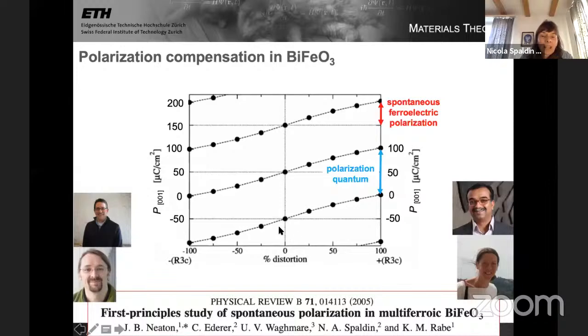And actually, this is something we knew already, although I guess I had personally not really registered the implications of this in 2005 with Jeff Neaton, Claude Ederer, Umesh Waghmare, and Karin Rabe, when we calculated the polarization as a function of the distortion in bismuth ferrite. Here you see the different branches of the polarization lattice. For the paraelectric undistorted phase, here are the values we just looked at, 50, minus 50, 150, and so on.